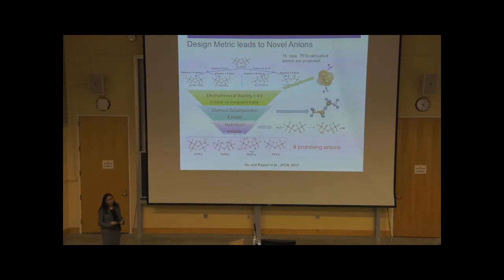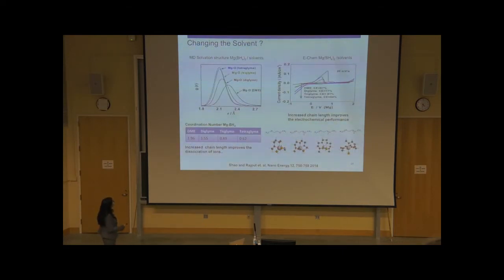But then we thought, what can we do with these salts which already exist, where we're simply trying to change the solvent molecule? So for this magnesium borohydride salt, we realized that if we can simply increase the chain length of glyme, so if we move from DME to tetraglyme, which has five oxygens, we can significantly increase the magnesium-oxygen interaction. And by simply increasing the interaction of magnesium with the solvent molecule, we can significantly decrease the coordination number of magnesium and anion, where the coordination of magnesium borohydride changed from 1.96 in DME to 0.62 in tetraglyme.